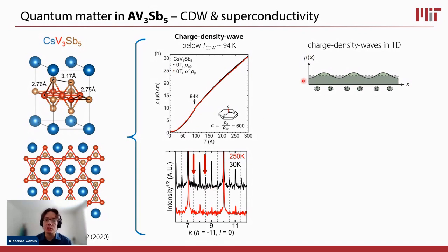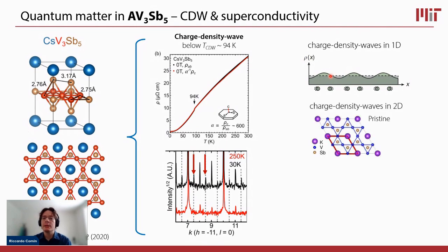And so we can have this gentle modulation of the electronic density as a function of the position on the lattice in one dimension at least. Or we can have, similarly, a distortion of the lattice. And a distortion of the lattice will cause also a modulation of the electronic density in the system. Now, in 1D, things are relatively simple. There's not really many configurations for the charge density wave. It's just a one-dimensional modulation of either the charge density or the lattice displacements. In 2D, things are more complicated, but also therefore more varied and more rich.